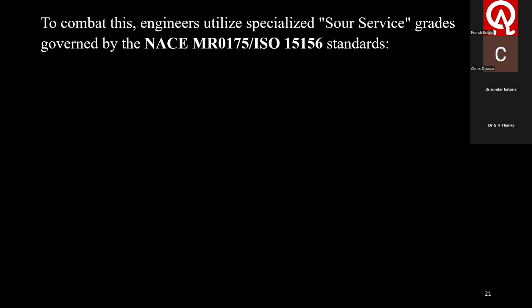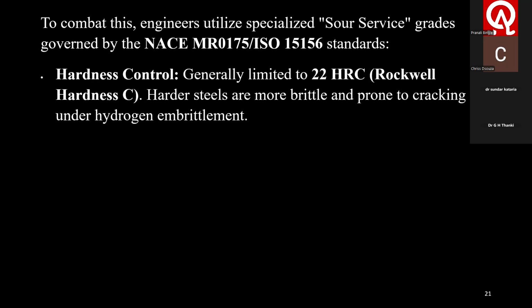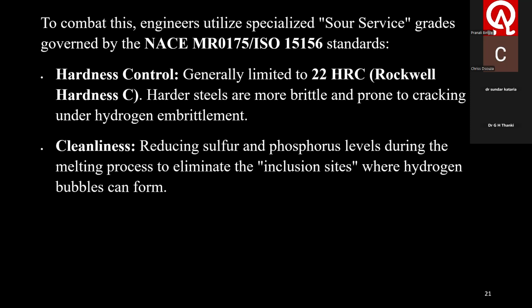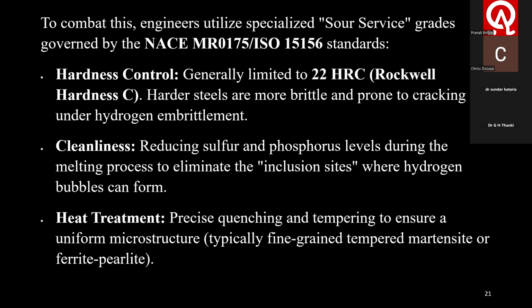To combat this, engineers utilize specialized sour service grades governed by the NACE MR0175/ISO 15156 standards. Hardness control, generally limited to 22 HRC, that means Rockwell hardness C. Harder steels are more brittle and prone to cracking under hydrogen embrittlement. Cleanliness: reducing sulfur and phosphorus levels during the melting process to eliminate the inclusion sites where hydrogen bubbles can form. Heat treatment: precise quenching and tempering to ensure a uniform microstructure, typically fine-grained tempered martensite or ferrite-pearlite.